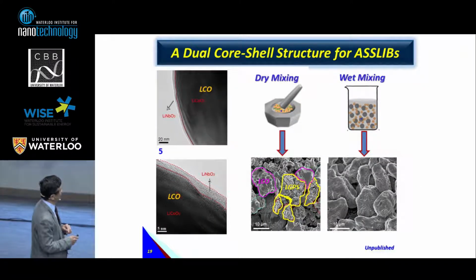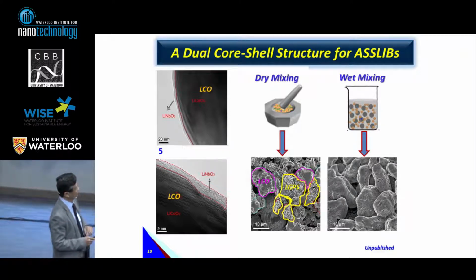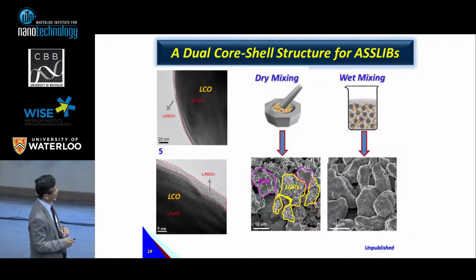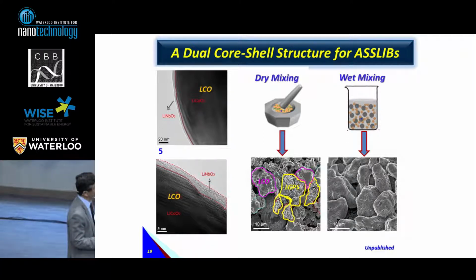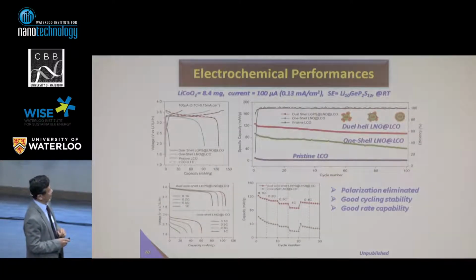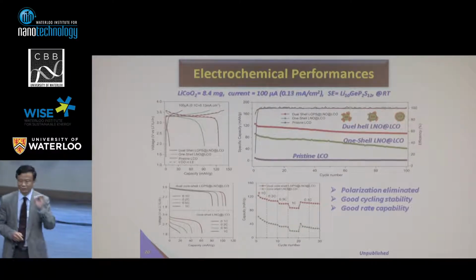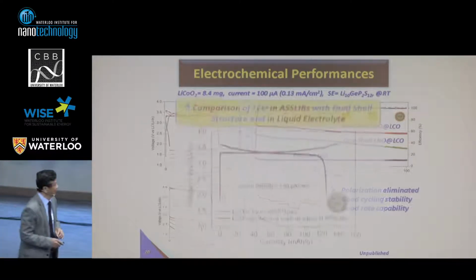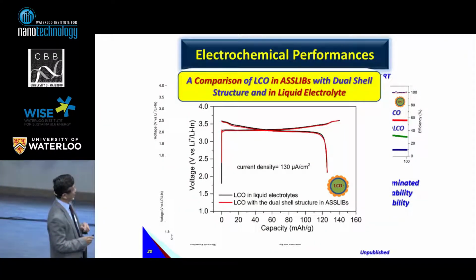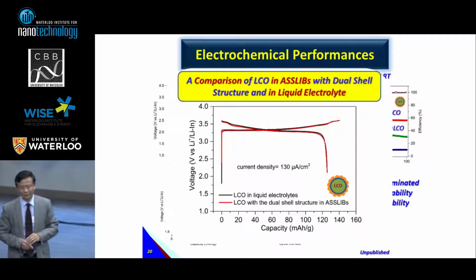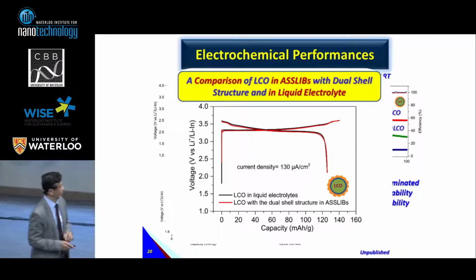For example, using ALD, you have a coating on the lithium cobalt oxide. The electrolyte process is also important. If the mixture by mechanical method is not uniform, using the chemical one is very uniform. So finally, we found that without coating, you see there is no capacity. With one layer of coating, not uniform, the cycling performance is not that good. With the two-layer coating, really good performance for solid state. So also we compare with the liquid. You see the liquid and solid totally overlap. So that means we can get that good performance.